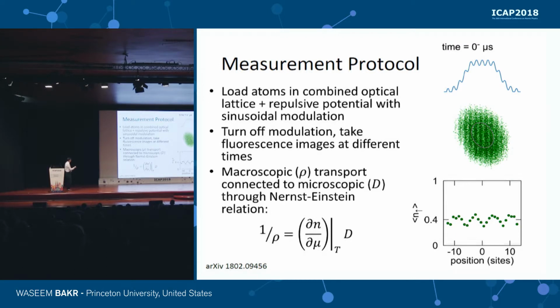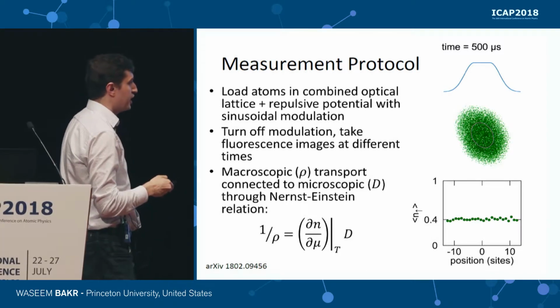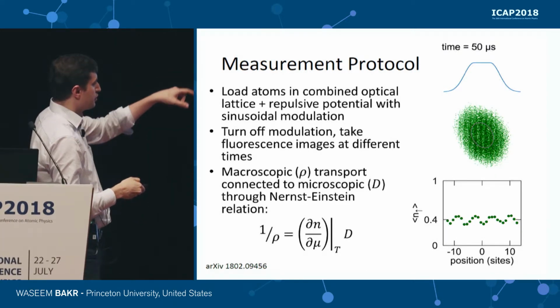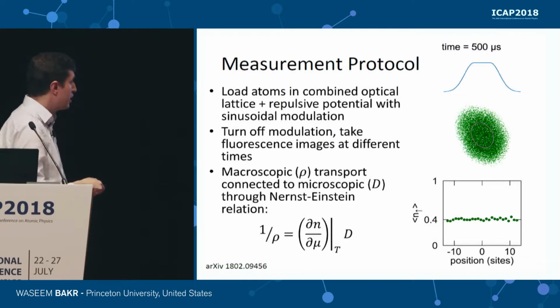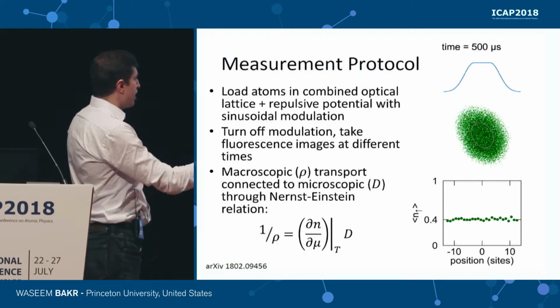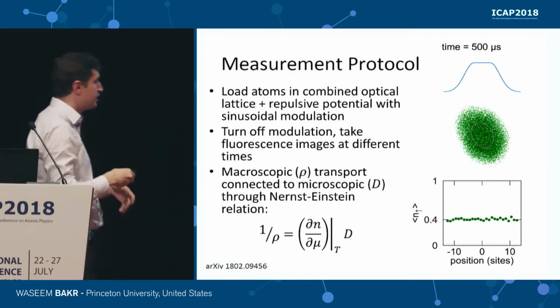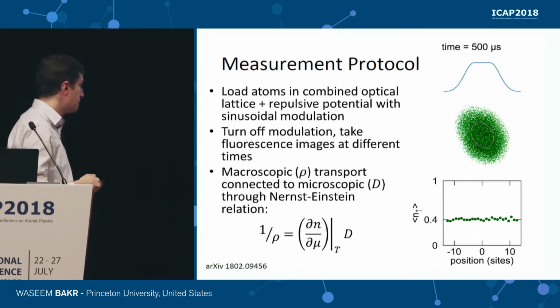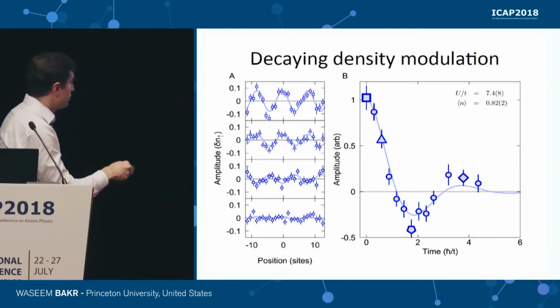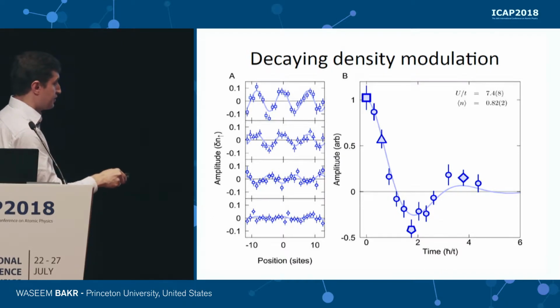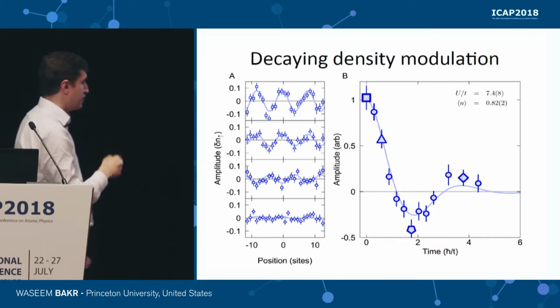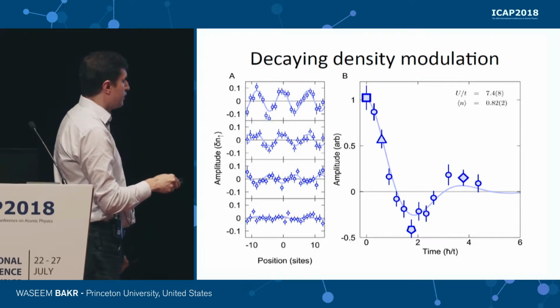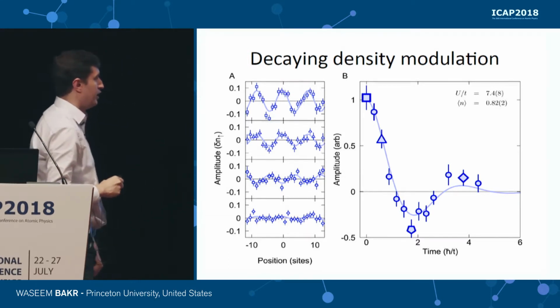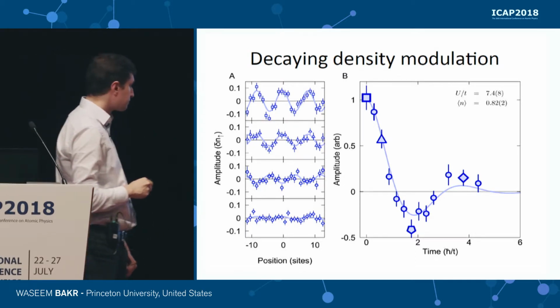Now this is just before we switch off the pattern, and then we switch it off, and this contrast starts to decay. It happens very quickly. This is 50 microseconds later. This is 500 microseconds later. We can fit the amplitude of this sine and track how this amplitude decays versus time. Here's this amplitude plotted versus time for a strongly interacting system, U over T roughly 7 or 8, and the density is 82% plus or minus a few percent.